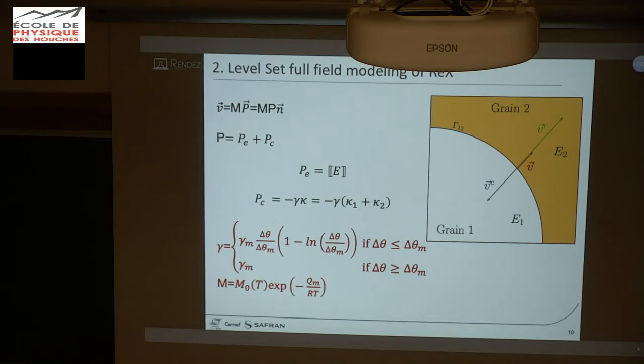But you can see that classically for grain boundary energy, we use the Read-Shockley formalism. Okay, you can see the classical Read-Shockley description of the grain boundary energy, which is related to the disorientation at the grain interface. And the mobility of the grain interface is classically defined like an Arrhenius law, where you can have a constant exponential term, M0, or one which can be defined as dependent on temperature, with an activation energy, with the classical Arrhenius equation. And generally, we use this kind of equation to simulate migration of grain boundary interfaces.